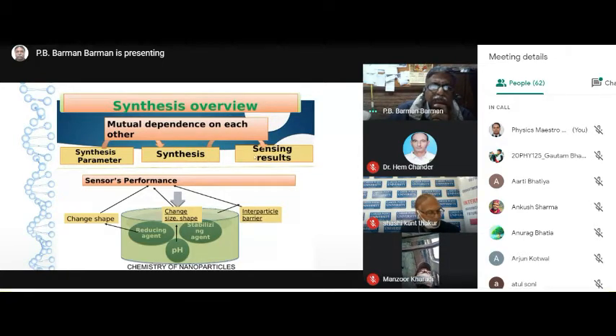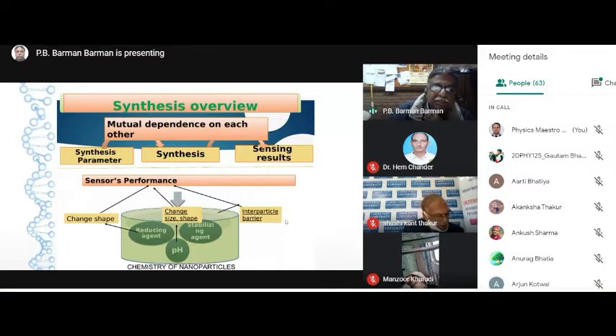So when we talk of sensor performance, it can be regulated through the change of shape or size, and of course the interparticle barrier. When we talk of capping the particle, what should be the capping such that the interparticle barrier could be maintained? If my interparticle barriers could be maintained, that means more and more surface area could be seen by the hydrogen, and it can be sensed properly.